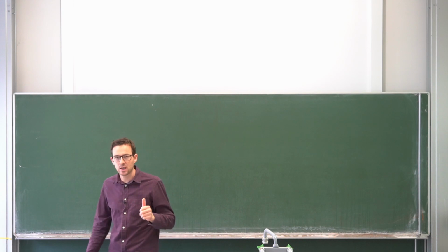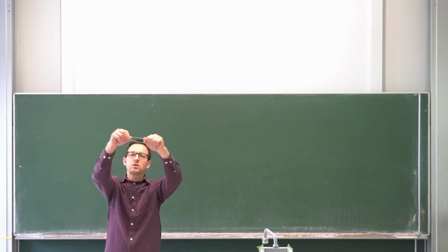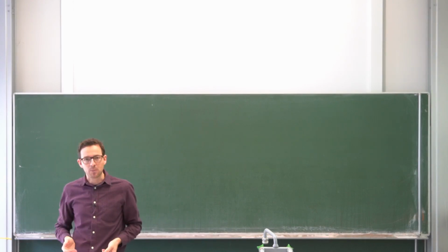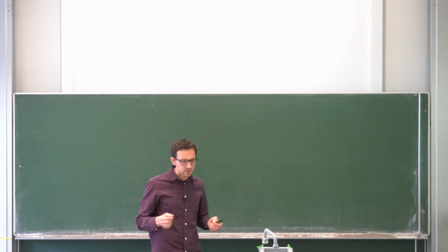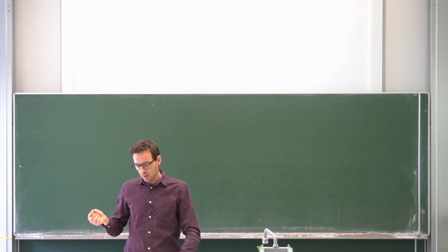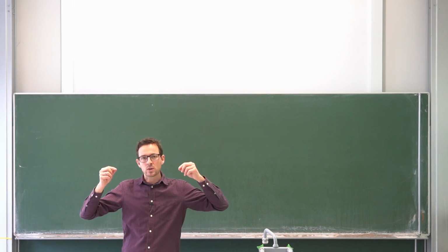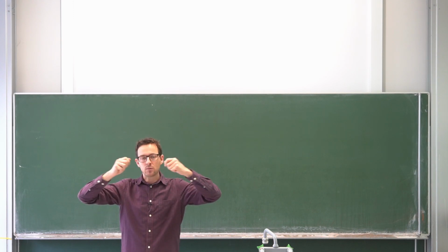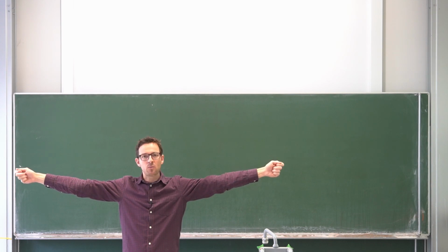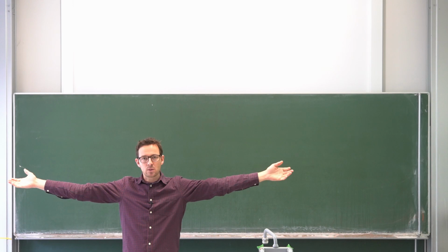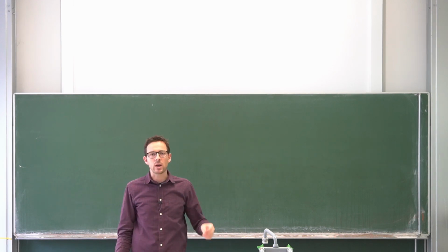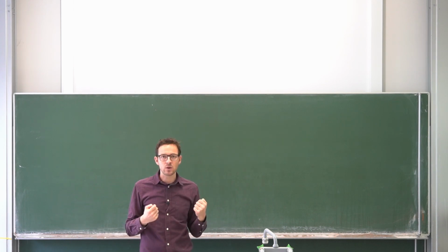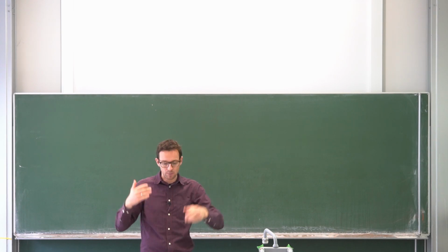Okay, firstly, what we want to understand is, why is a rubber actually elastic? So if I stretch it, why does it come back? Okay, and in order to do this, we first put up an intuitive picture, and that is the picture of a polymer coil. So you can intuitively, now we understood that because of entropy, because of the numbers of microstates, a polymer wants to coil up. And as we stretch it, we decrease the number of microstates. And this, of course, is not favorable in terms of entropy. So our intuition will tell us that the polymer will have a tendency to pull back if we let go, to increase the numbers of microstates.